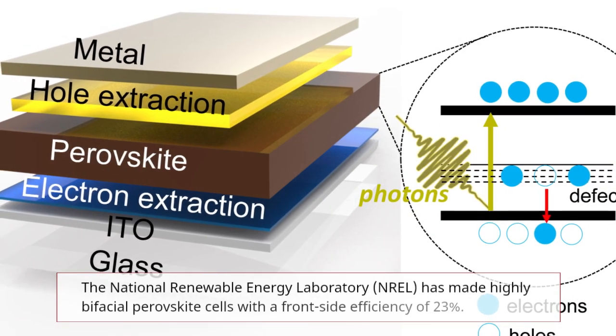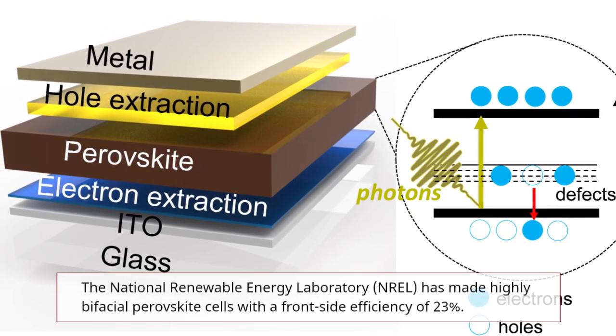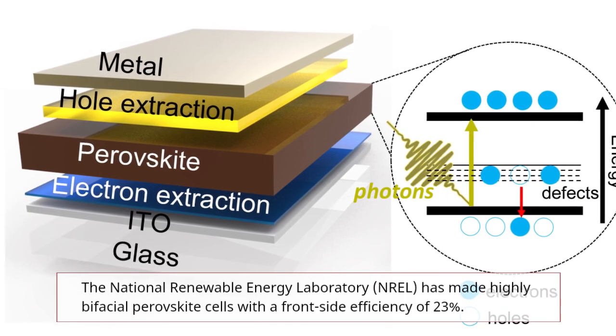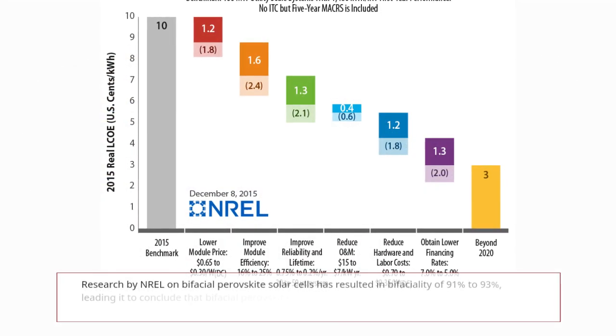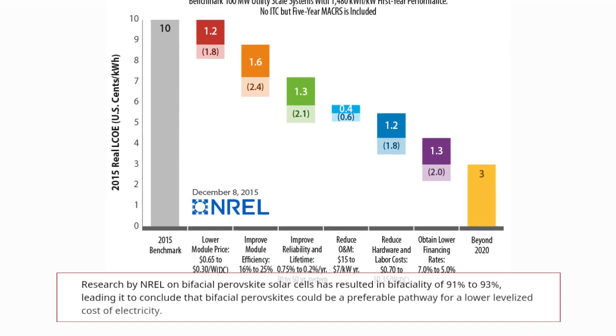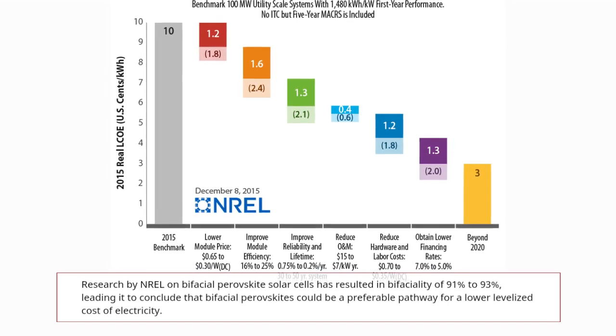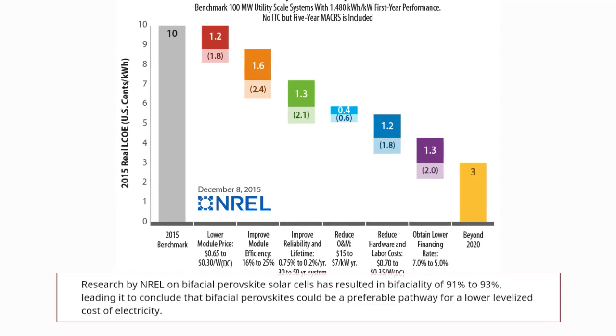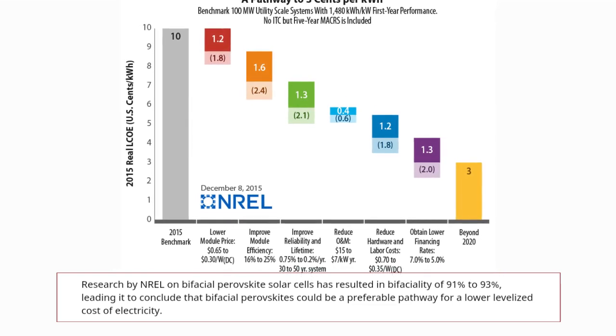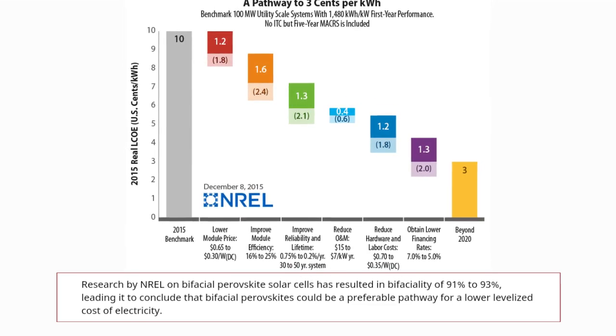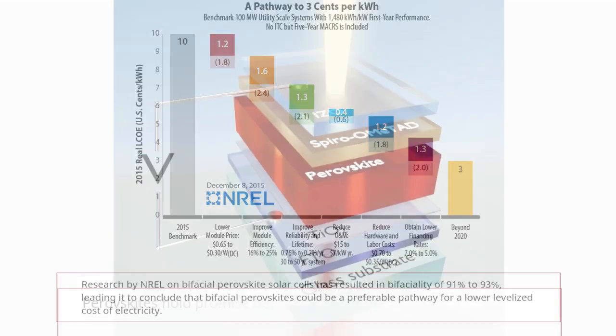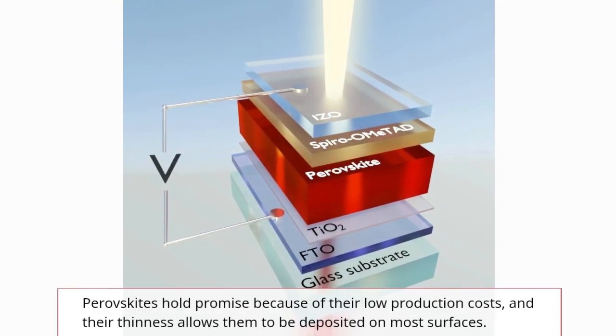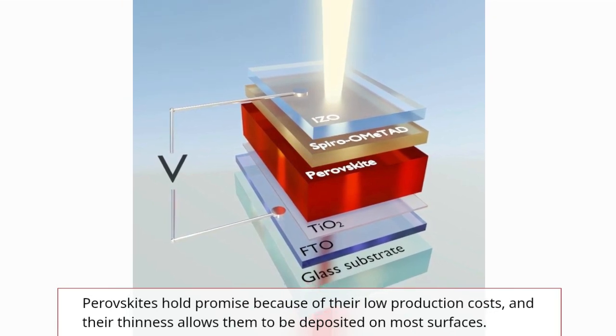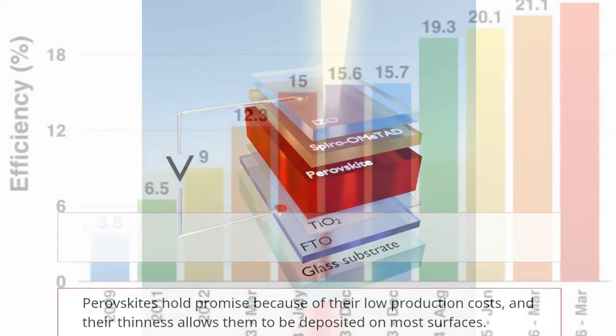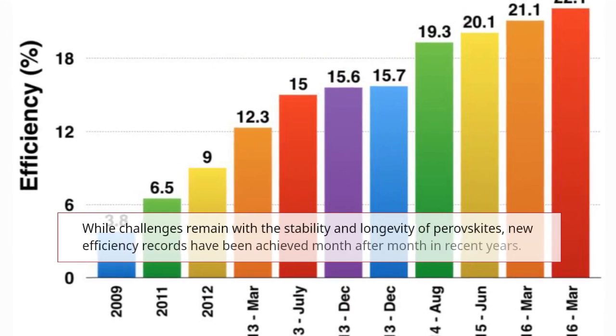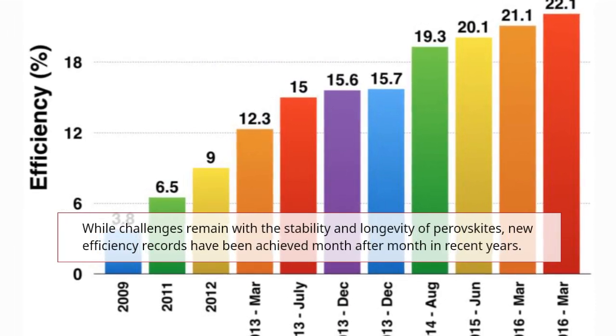So NREL has made highly bifacial perovskite cells with a front side efficiency of 23%. The research done by NREL on bifacial perovskite solar cells has resulted in a bifaciality of 91 to 93%, leading it to conclude that bifacial perovskites could be a preferable pathway for a lower levelized cost of electricity. Perovskites hold promise because of their low production costs, and their thinness allows them to be deposited on most surfaces. However, there are still challenges that remain, such as the stability and longevity of the perovskites.